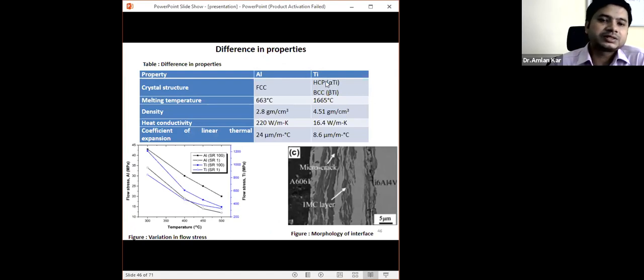If you take aluminum and titanium, you understand that there is a substantial difference in their mechanical and physical properties, and because of that, aluminum is recrystallized, but the titanium is subjected to some sort of fragmentation. And during the fragmentation, you can see there is a development of microcracks and an intermediate layer at the interface. And these are brittle particles which have been fragmented and distributed in the aluminum matrix, and because of that we get a composite property of the weld.